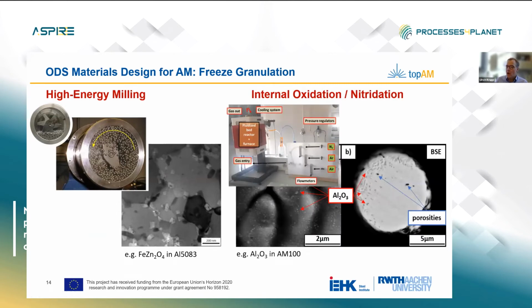Another way that we are exploring is an internal oxidation and nitridation by adjusting the oxygen or nitrogen pressure in a fluidized bed system. Then we can obtain really nanoscale alumina or, for instance, titanium nitride particles, and they stay stable when they are applied to the operation environment in process engineering.